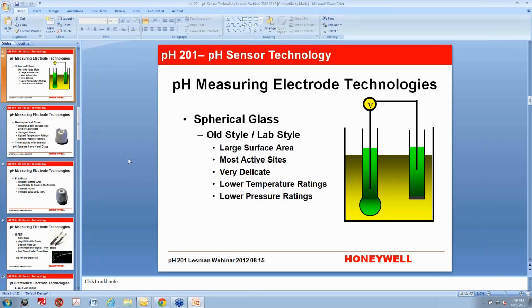It has an extremely large surface area, which is nice because the surface area relates to how long the sensor lasts in terms of how many active sites you have that the hydrogen ions can land on. So it has the largest surface area, and so therefore the most active sites. However, it's very delicate due to its physical construction. It's very easy to break the glass either by mishandling, say in a beaker when you're doing a buffer calibration, or just in the process.